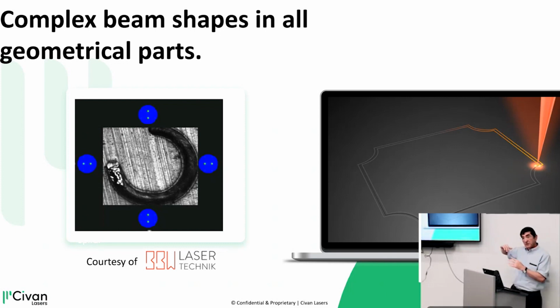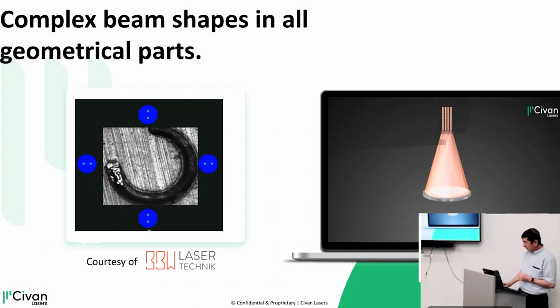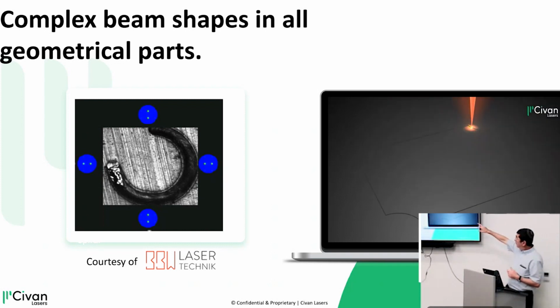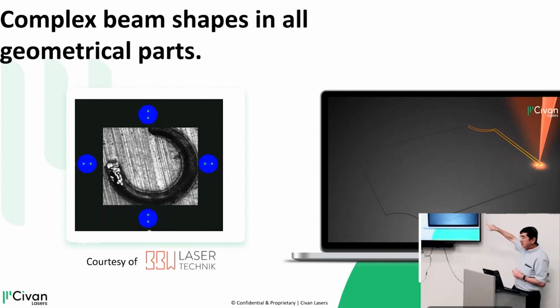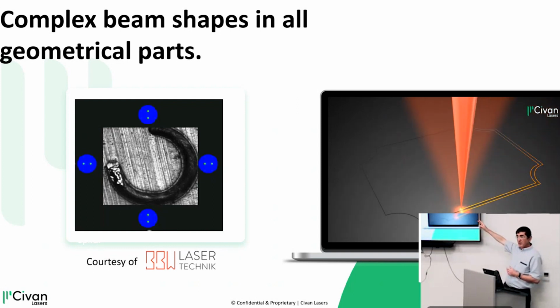But the orientation of the beam shape relative to the propagation direction is critical. In this case, we have to be the 2 points that are perpendicular to the propagation direction. So if you would have some optics that creates instead of 1 point, 2 points, it's not enough, because as you go along on your workpiece, the orientation has to change. And it has to happen very, very fast.